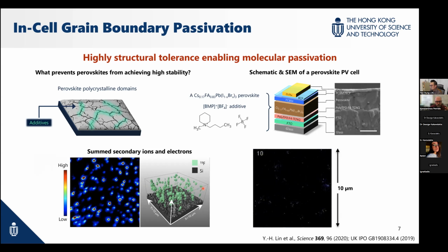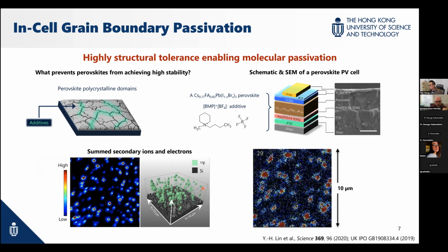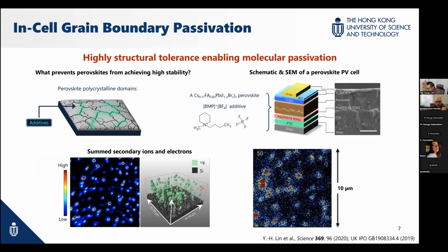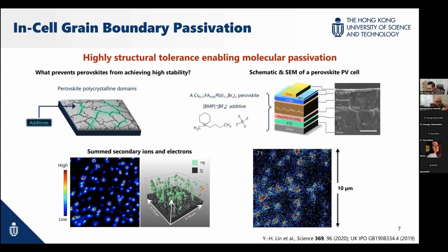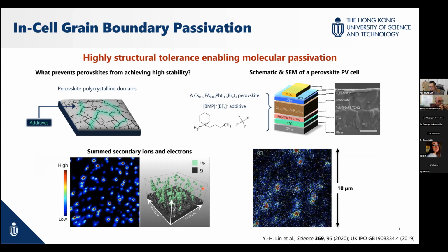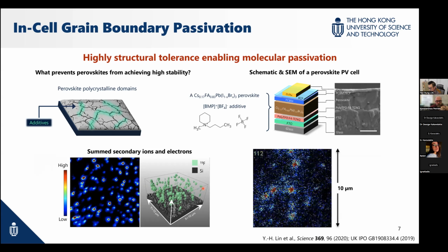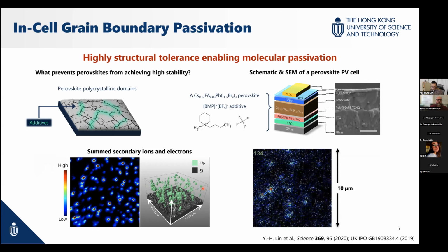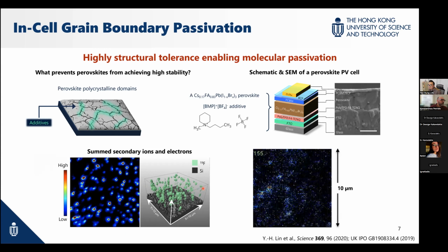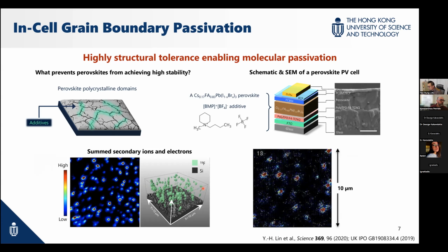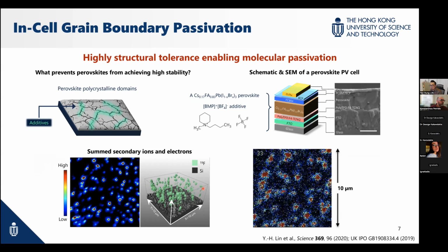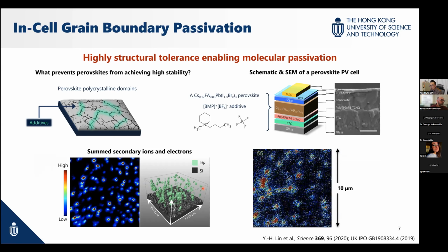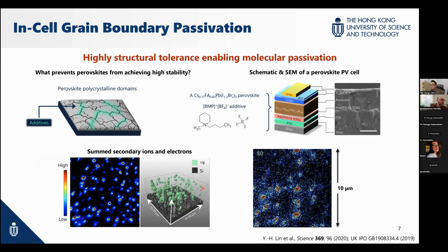This kind of behavior is mostly approached by the community because what we believe is that the very vulnerable part of perovskite is at the grain boundary, this apparent grain. So with this additive being pushed out, what we believe is it will stop the material decomposing from coming out. And we're going to look at that in a minute.